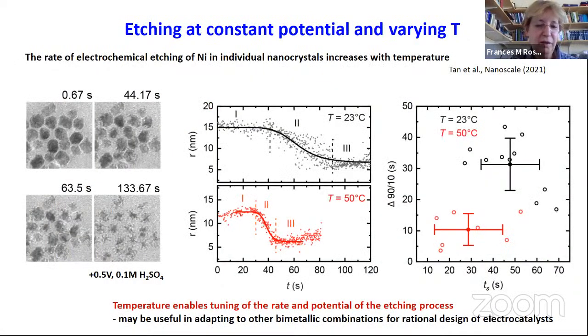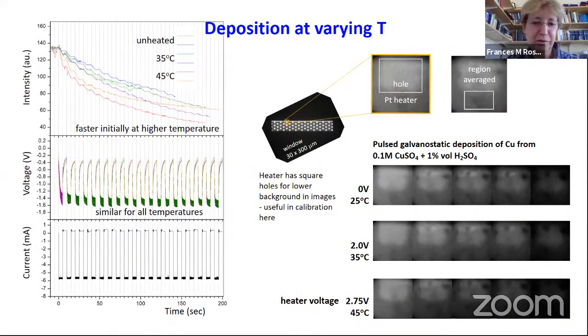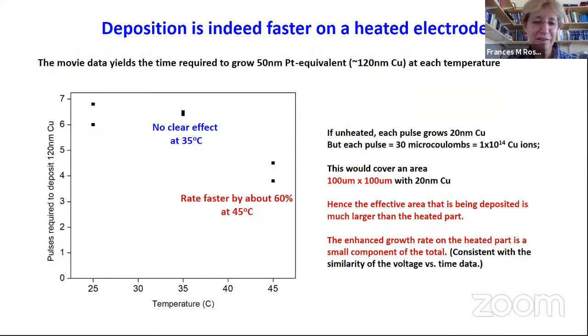And here's a slide showing the etching reaction of nickel that I showed you a movie of earlier. This being done at 2 different temperatures, you can see somewhat of a difference in the kinetics of the etching of individual objects because of the higher temperature. Here's another example where we deposit copper on one of these heated windows, and we just measure how fast it deposits. And what we find indeed is that deposition is faster if you heat up the experiment. So not really surprising, but at least it's a proof of principle experiment.